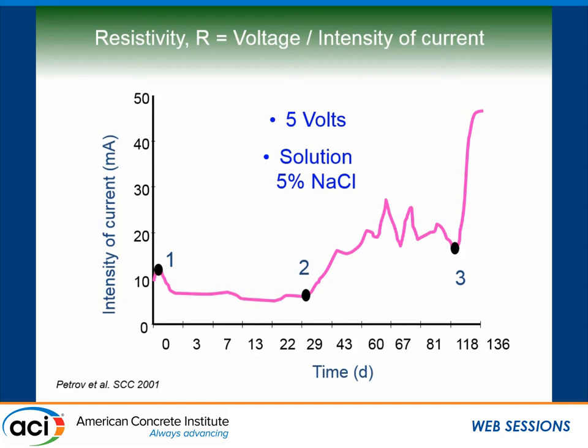Okay, I'll just show you one example of the type of response you get. So this is one of the rebars, and the time here, the intensity of the current. So initially you have a certain current, and then after about 30 days you have an increase in current, and this is the onset of corrosion. And then current is increasing because you're starting to have corrosion, expansion, cracking, and then serious cracking, and it takes off. So what I'm going to compare is the effect of surface settlement on this onset of corrosion.